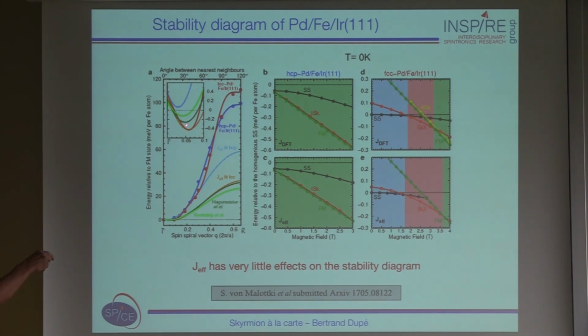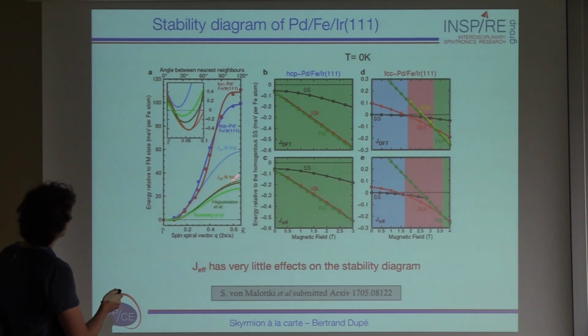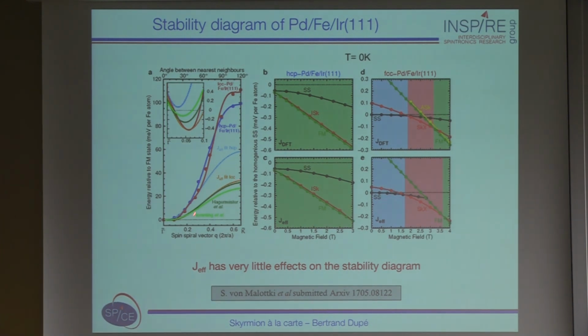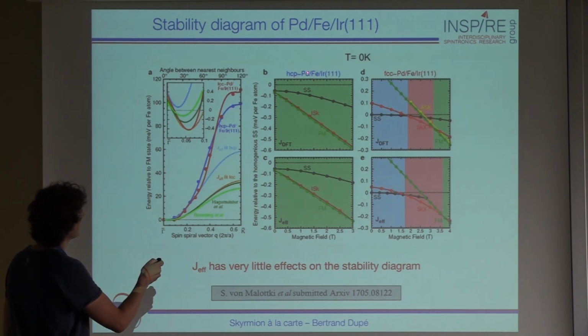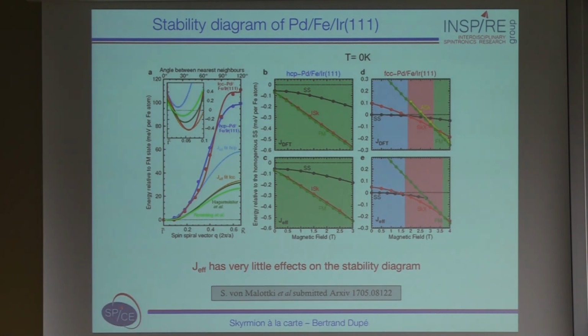So here, I will only focus on the set where we actually want to model correctly the curvature of the minimum. So this is the red curve, the J effective for the FCC, and the J effective fit for the HCP. So on the right part, you have what we call the stability diagram at 0 Kelvin again, for the full DFT set of J, and for the J effective for palladium HCP and palladium FCC. So you see that these two diagrams here for palladium HCP iron on iridium are actually pretty similar. So what you can say is that in this case, HCP, there is not so much difference between J effective and the full set of J obtained by DFT calculation.